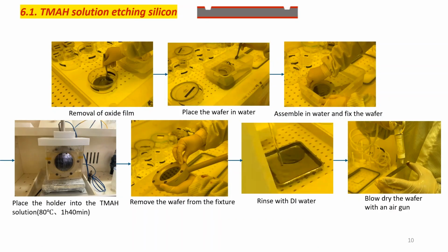Now part of the silicon surface is exposed to the air. Silicon etching can be performed. First, remove the oxide layer that was briefly exposed to the air. Then place the wafer in water to prevent reoxidation. Then assemble the fixture to fix the wafer. Then place the fixture in the TMAH solution, etching at 80 degrees for 1 hour and 40 minutes. Then remove the wafer from the fixture. Rinse the wafer with DI water, and finally blow dry with an air gun.